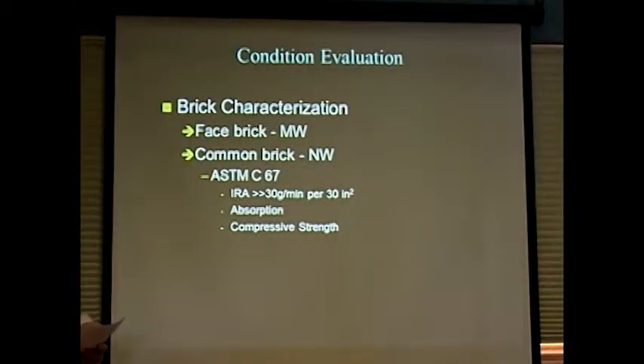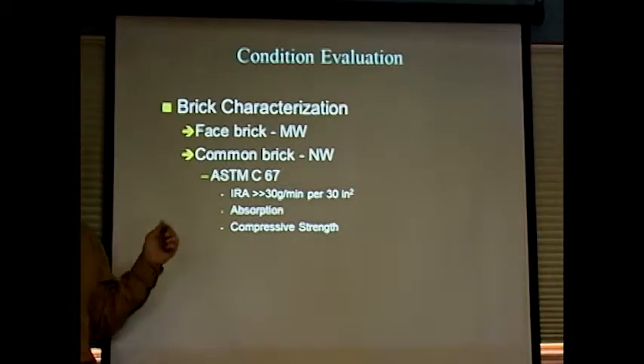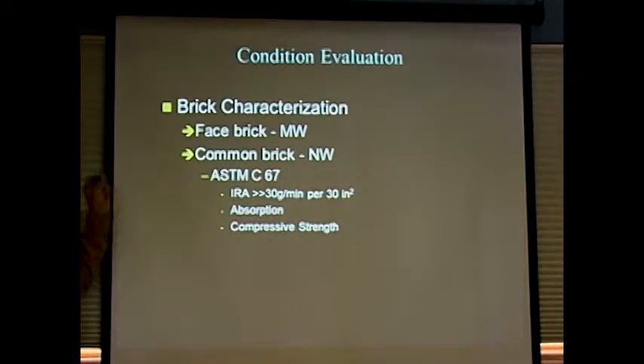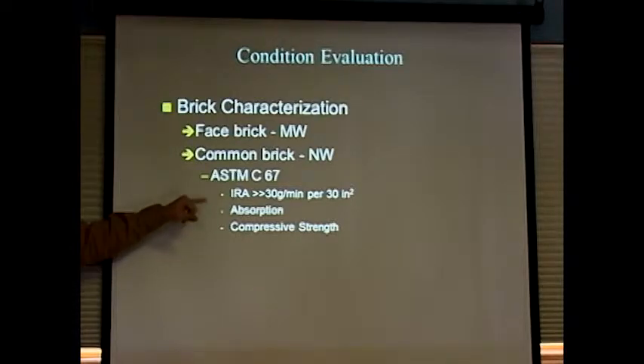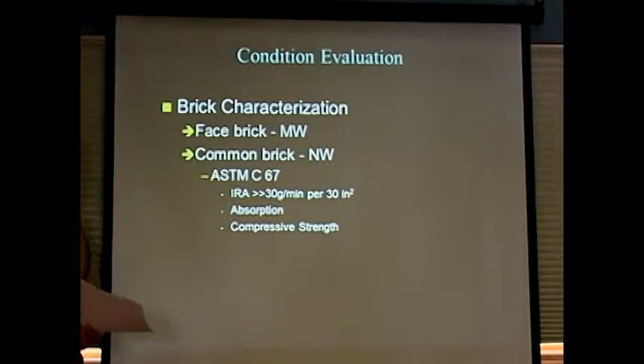We also tested brick. It really wasn't necessary as part of the project, but remember, a component of the solution here was looking at injection of internal voids. And to design an appropriate injection material, we need to know basic characteristics of the brick, how strong it is, how absorptive it is, and that goes into designing our compatible injection material. But what kind of struck me was that these were hugely absorptive brick. They had an initial rate of absorption much greater than a typical limit, which is 30 grams per minute per 30 inch squared, that we see in a lot of modern specs.